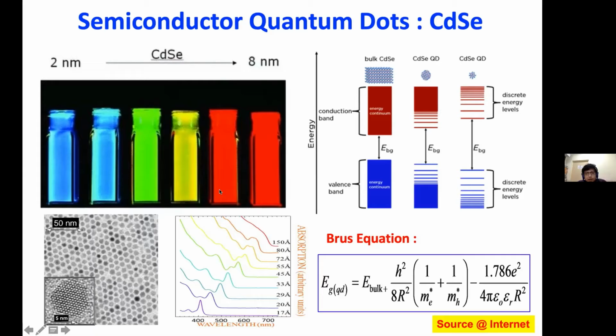Why is it happening? This is happening due to quantum confinement, because those quantum dots are basically zero dimensional, and the electrons and holes are confined, and due to the confinement, the energy changes. Here is the band gap energy of bulk cadmium selenide. Now, if the dimension reduces, the energy levels for electrons and holes are split, and the effective energy gap increases. So this is the energy gap for a cadmium selenide quantum dot.